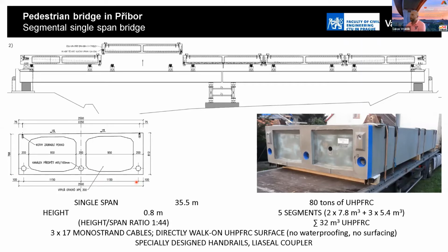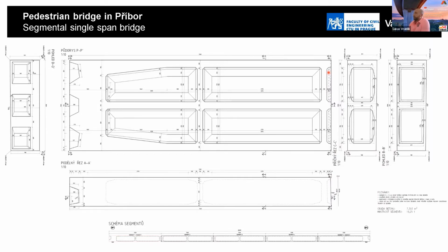And the geometry of the tendons was described by the basic statical behavior. As I said, it is a single span structure. That means the main loading is the dead load, the self-weight of the structure. So the shape of the prestressing tendon was described by a second order parabola. And this second order parabola produces uniformly distributed equivalent loading. And this loading was the same as the loading due to the self-weight, with opposite direction. This is the definition of the segments situated above the abutments.